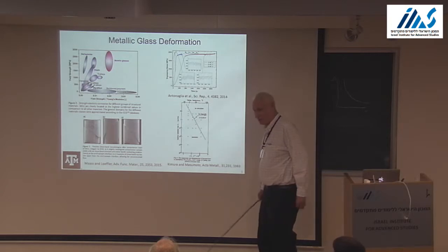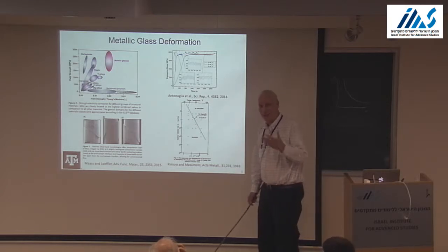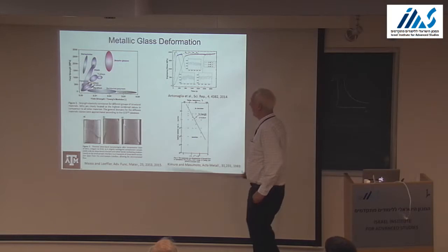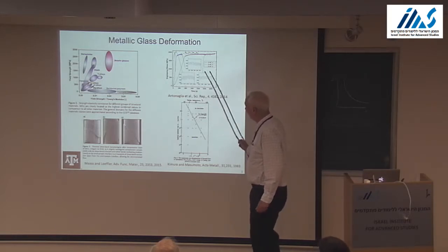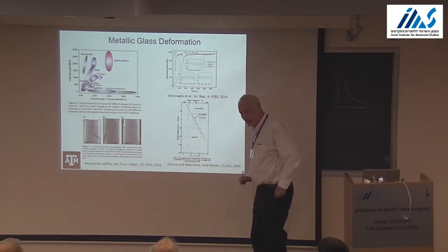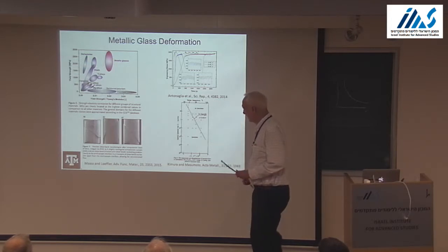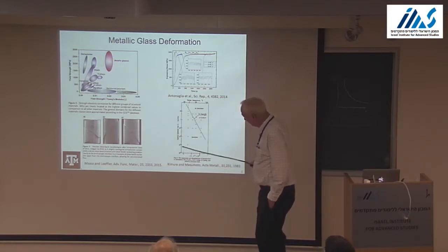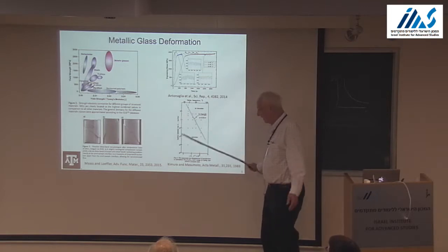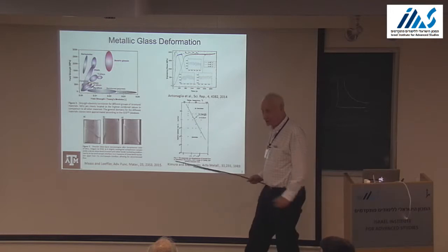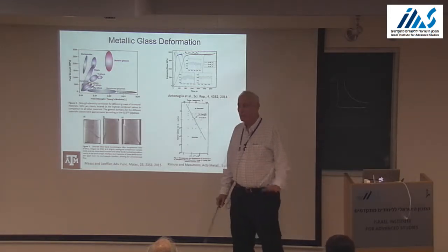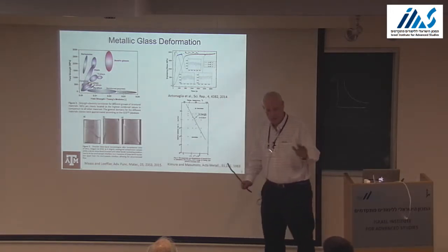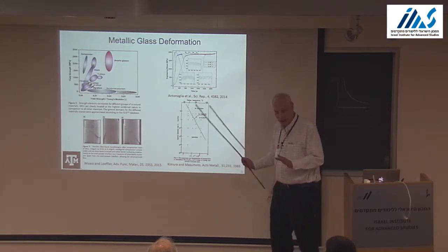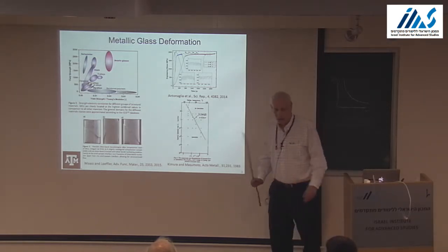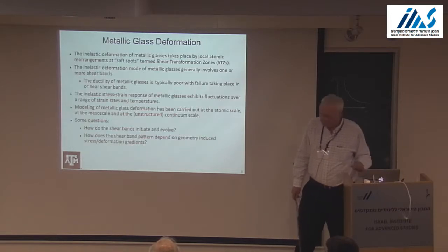Stress-strain curves have lots of, now I know to say, fluctuations, not wiggles. And very interesting, they're rate dependent. The period of them is rate dependent. This shows there's a range of strain rates for a given temperature where, at high enough strain rates, the wiggles disappear. So the fluctuations' amplitude and period can change, and it's temperature and strain rate dependent.